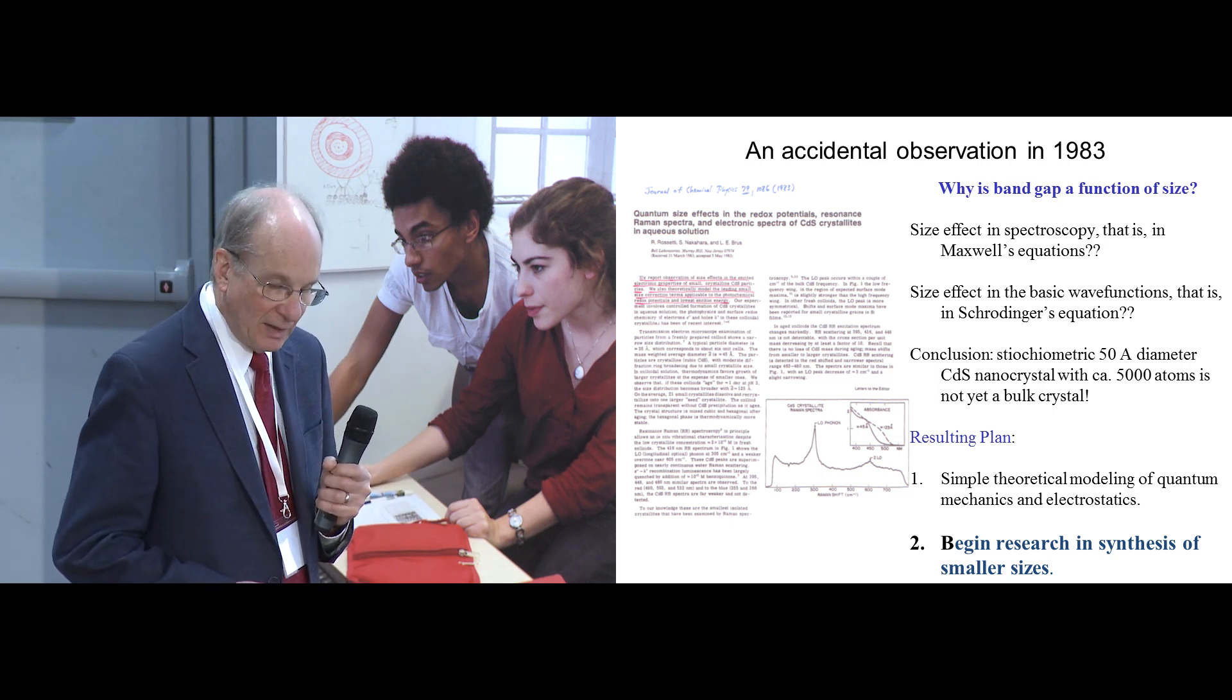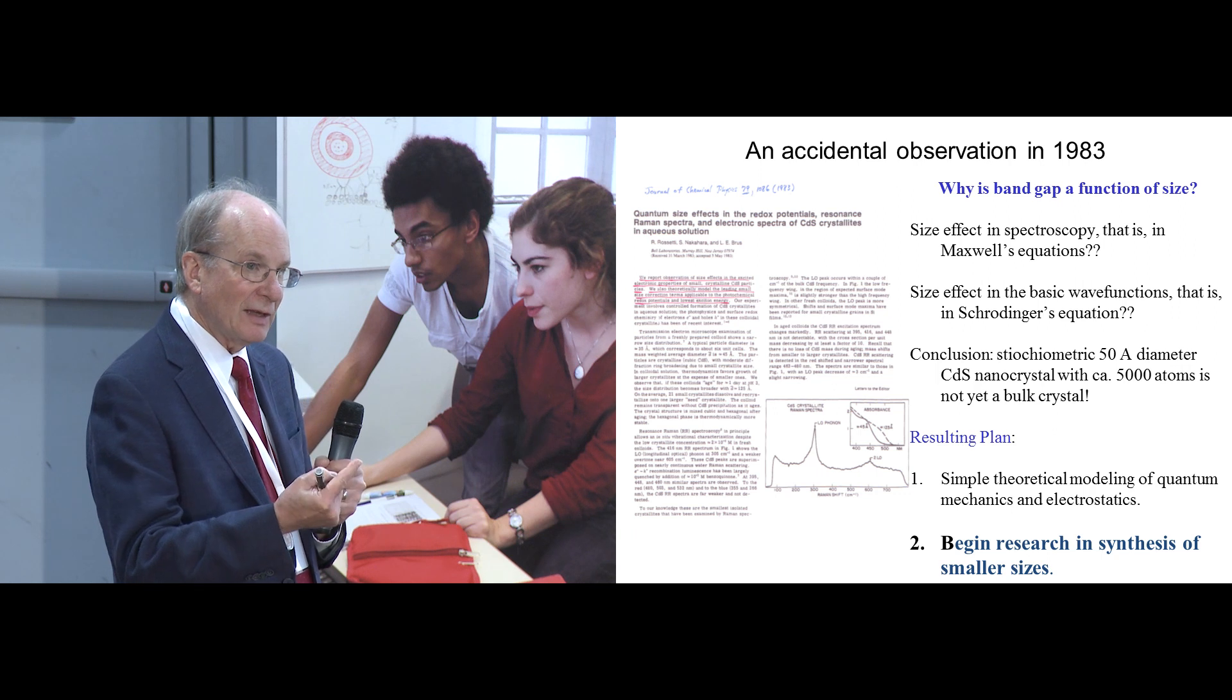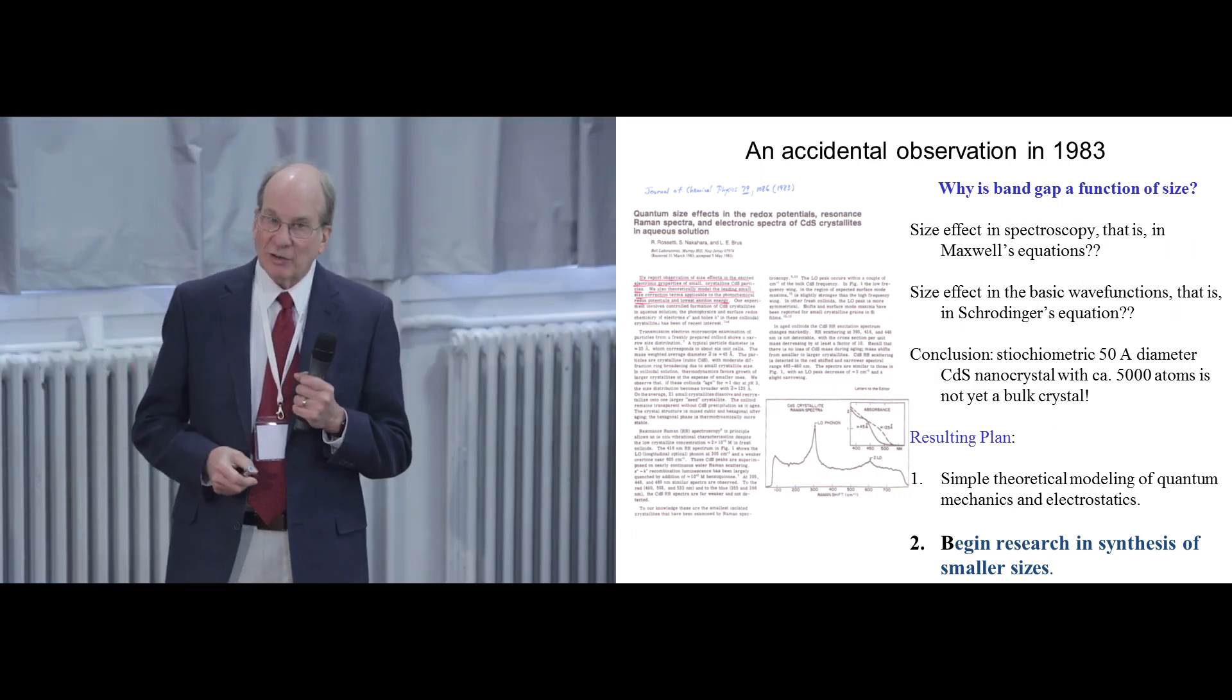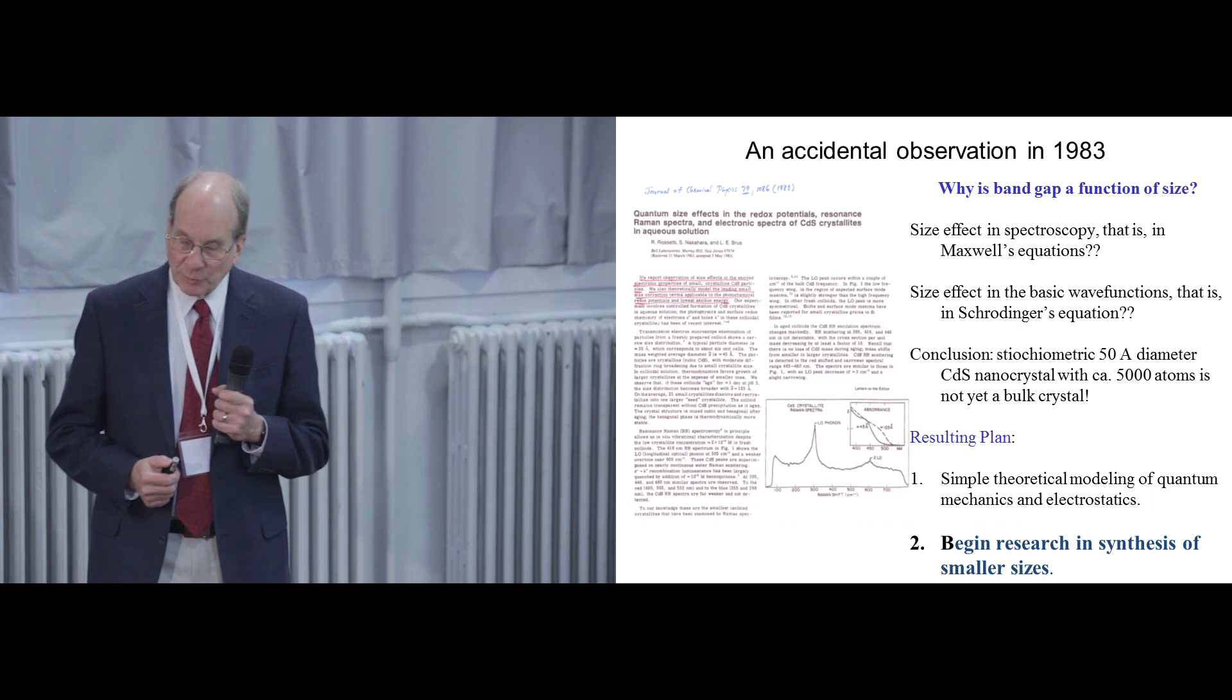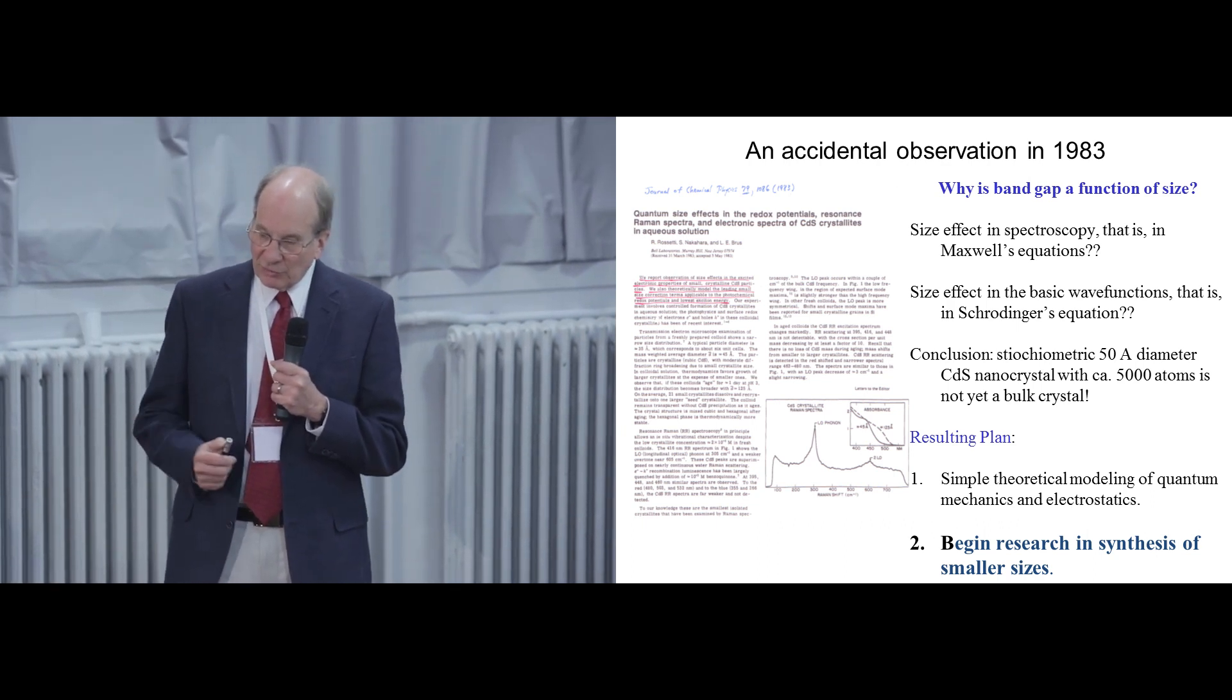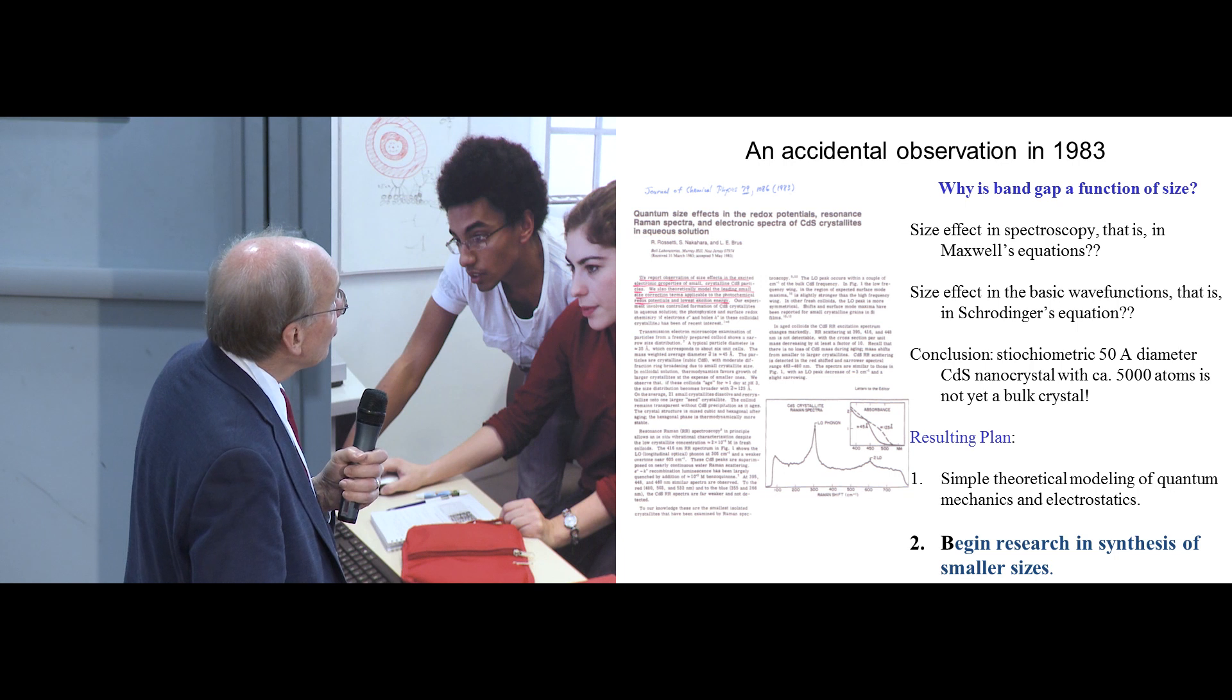In Mie theory, there's a resonance in the optical absorption cross section when the wavelength is the same as the diameter of the particle. But these particles are a factor of 100 smaller than the wavelength of light. And in that limit, the absorption spectrum should be independent of size and the intensity of the spectrum should scale as the volume of the particle. So it was not Maxwell's equations.